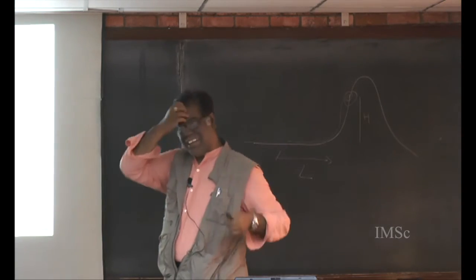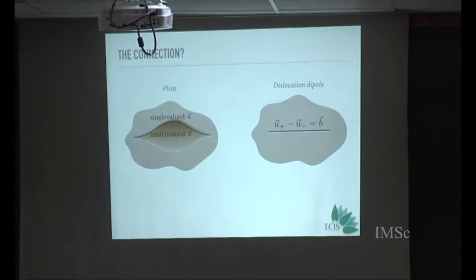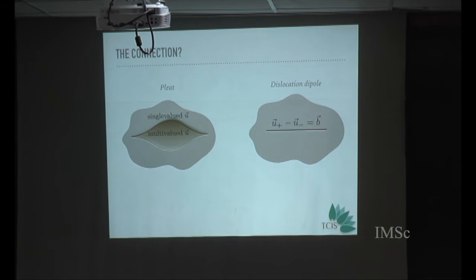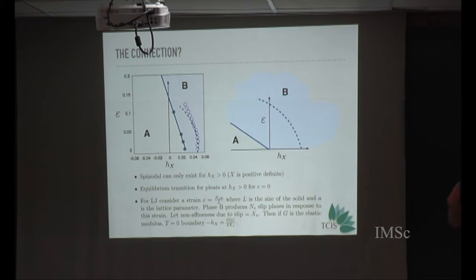And then that gives you the yield point. It's somewhat more than that because there seems to be a very deep connection between a pleat and a dislocation dipole. If you have a pleat, your displacement is single valued outside the pleat and multi-valued inside. This is similar if you have a dislocation dipole because there is a jump in the displacement as you go across this line. There is a branch cut, and this is just the Burgers vector. So there seems to be a deep connection.